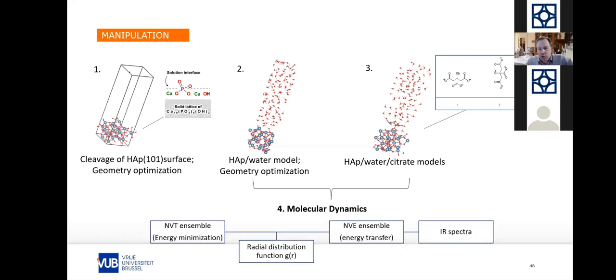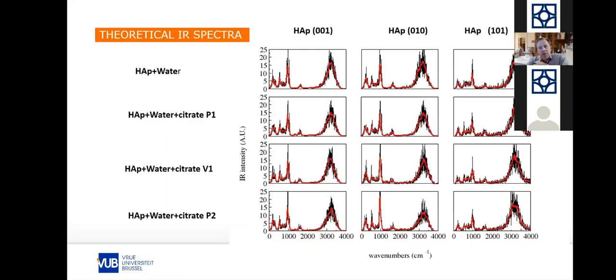We did our molecular dynamics calculation again in NVT, and then we calculated the radial distribution function. Then we moved to NVE, and with this data we extracted our dipole moment in order to obtain a spectrum, the infrared spectrum. These are the data. So we compare with the experiments. What you see here is our raw data, for the different situations: without citrate and with citrate, the three orientations.